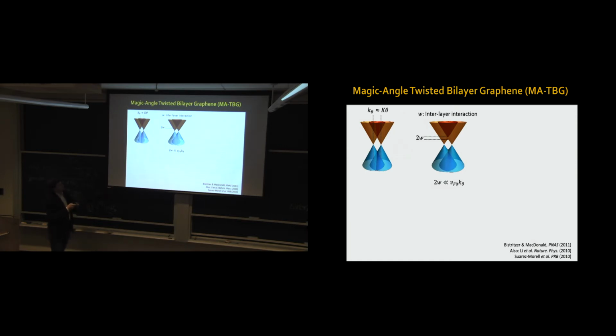This is the situation that occurs when the interlayer interaction is smaller than the energy at which that crossing point occurs. If I reduce the angle, the two Dirac cones get closer and closer. As the angle gets smaller, at the intersection point there is level repulsion which flattens and brings one band down. As I get closer and closer, eventually this flattens to the bottom, to 0 energy.